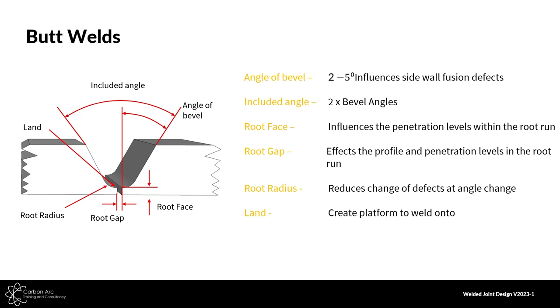We said before that the more we decrease the angle of the bevel, the more likely it is we would have weld defects. So why would we go to 2 to 5 degrees? The reason is that this type of joint design is very good for automated or mechanized welding processes such as orbital TIG welding, where we are not relying on welder skill to catch the sidewalls — we can preset machines to do that and reduce our risk.